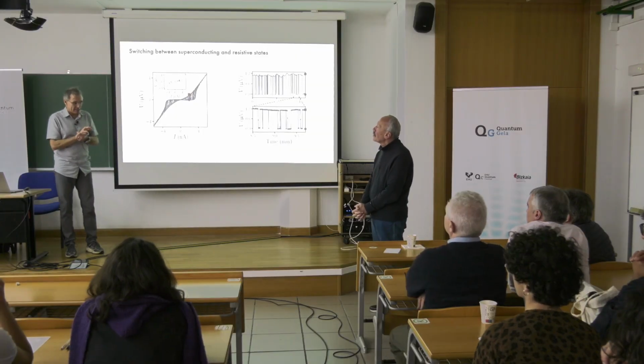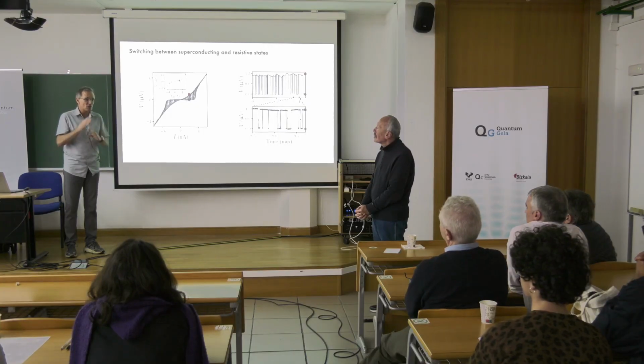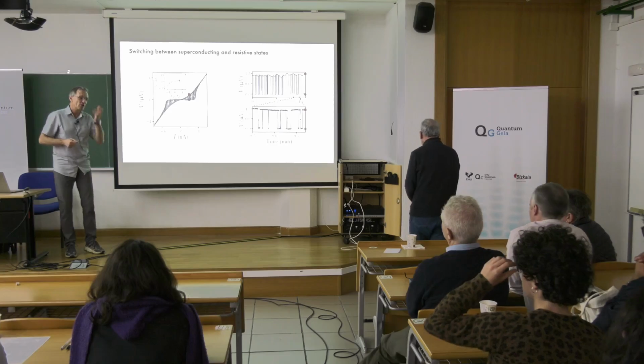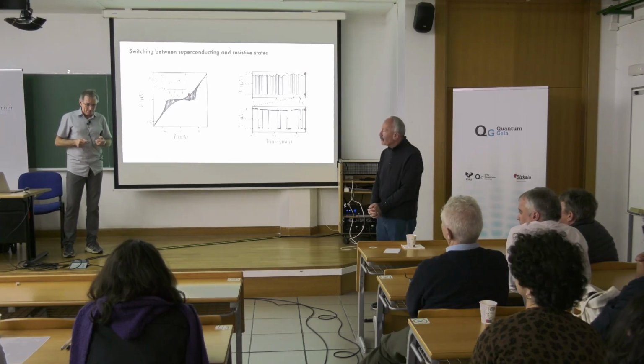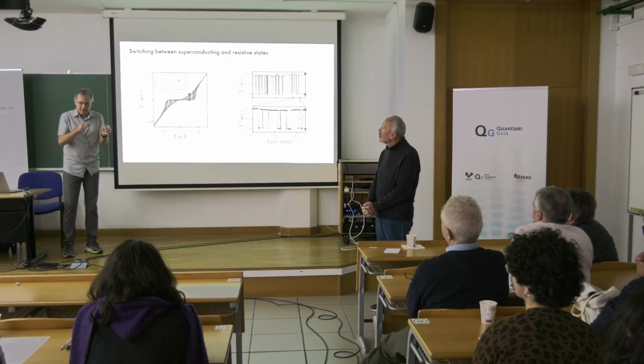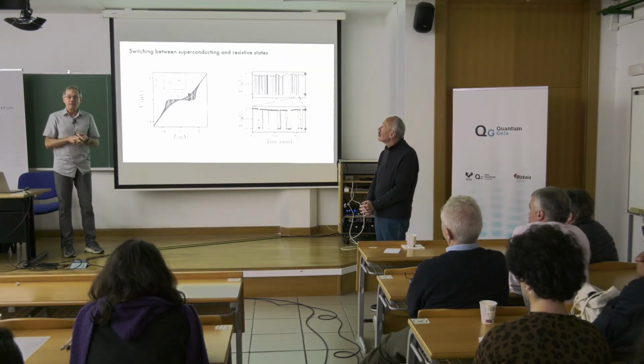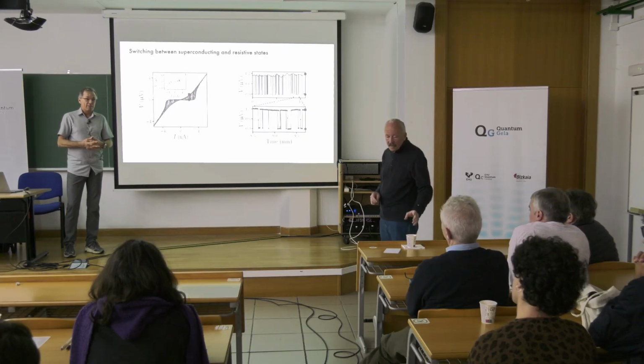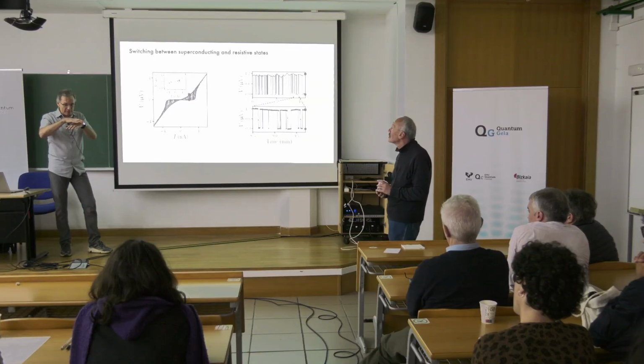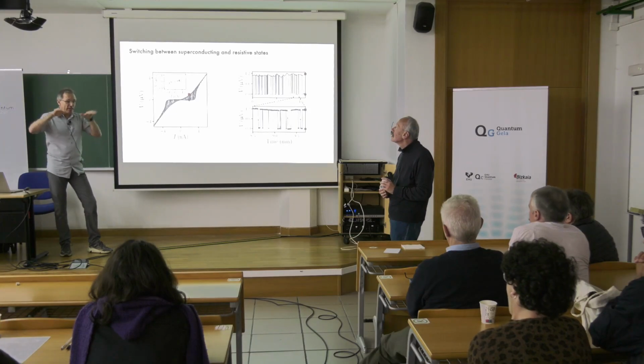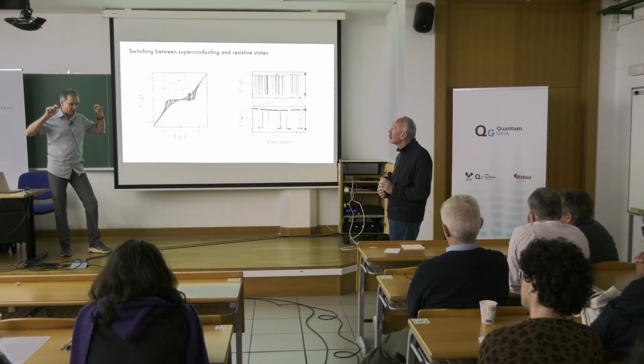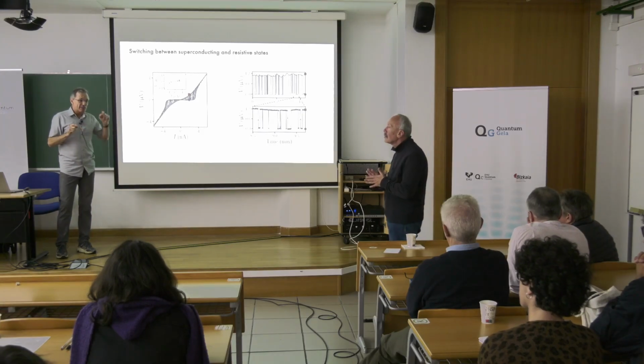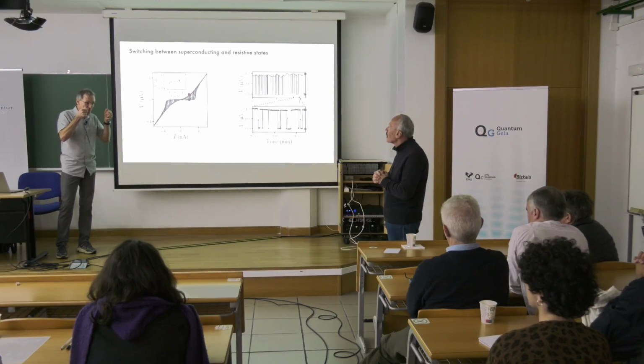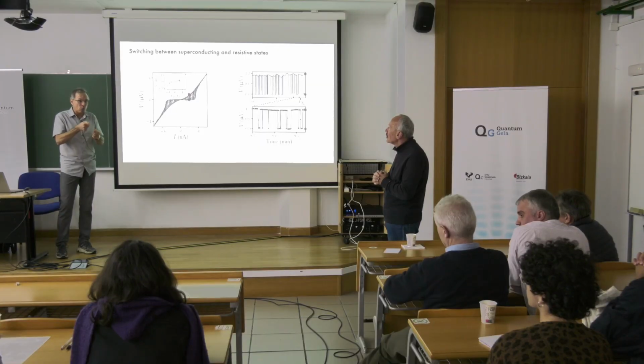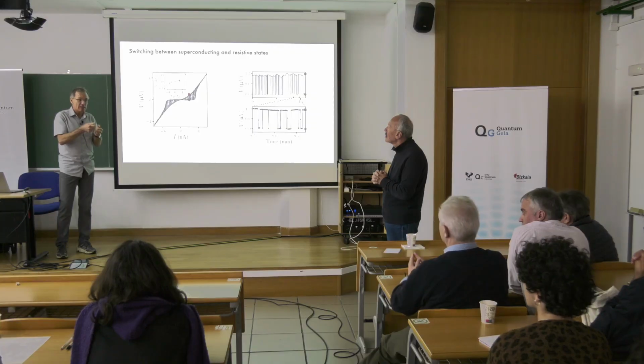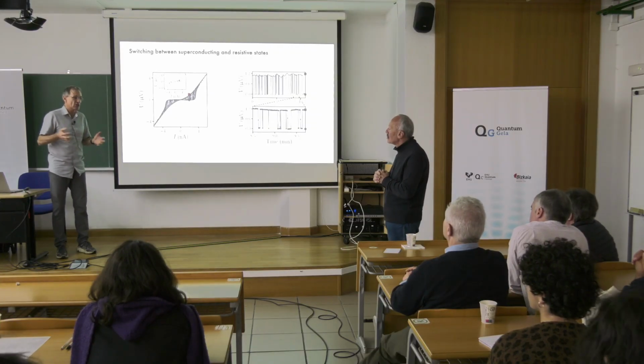Graphene is, from one side, simple because the band structure of graphene with these Dirac cones was calculated, well, not a century ago, but almost in the 40s. And it has weak interaction and so on, so these Dirac electrons can be calculated. But then when it comes here, the prediction from the band structure was that there would be flat bands, which means that the spectrum would be very flat, very narrow bands. And when you have narrow bands, then electron interaction becomes of major importance. And then to predict not free electrons but strongly interacting electrons is much more difficult.